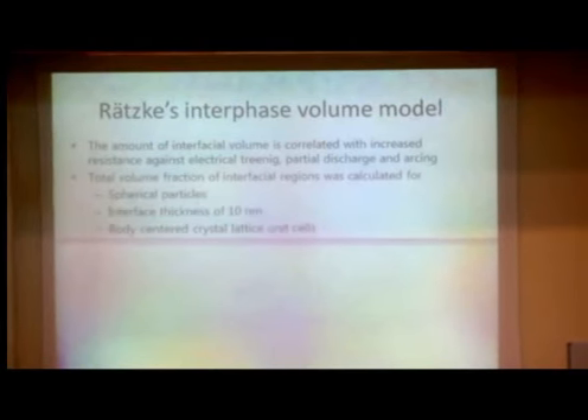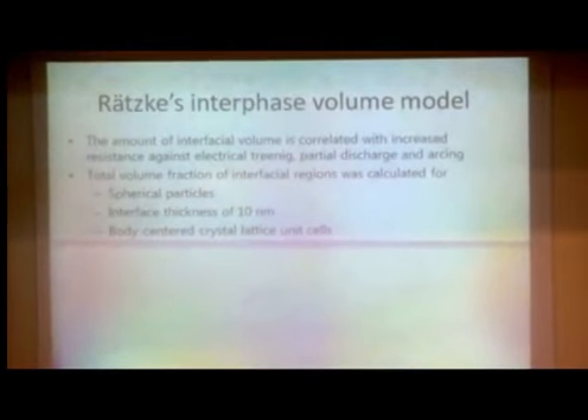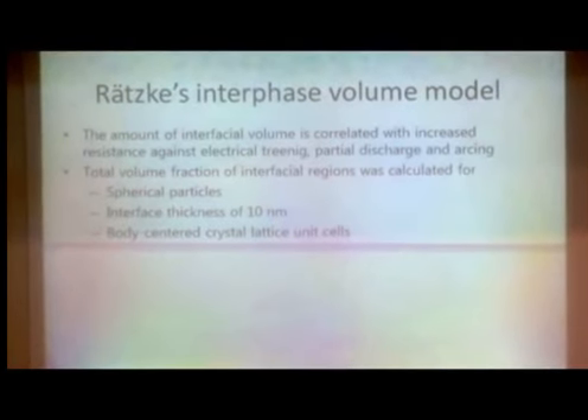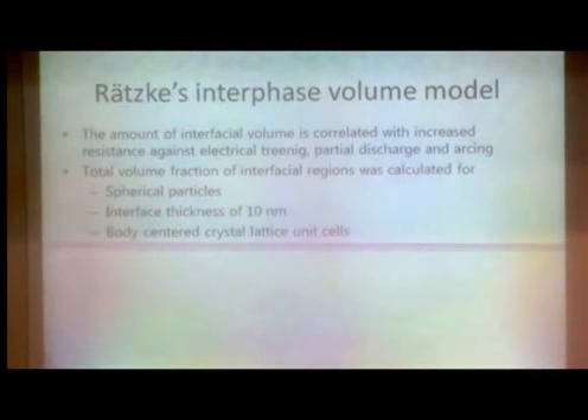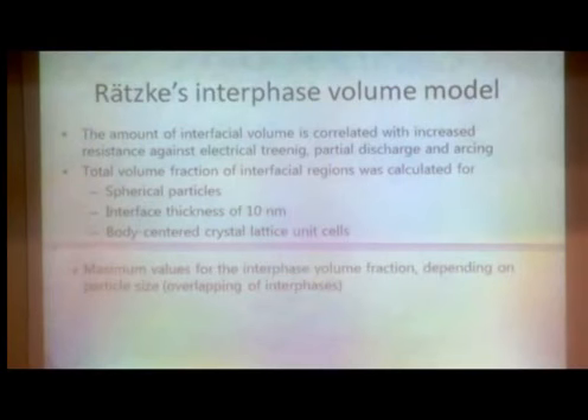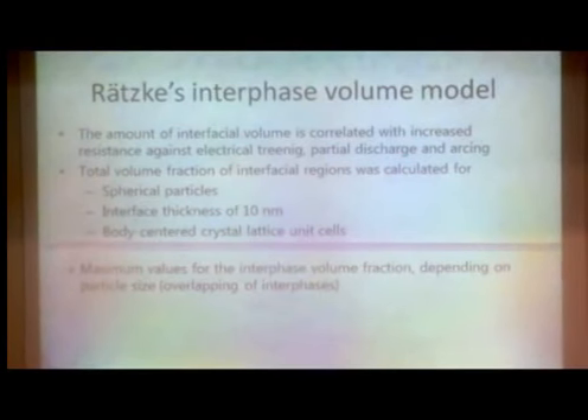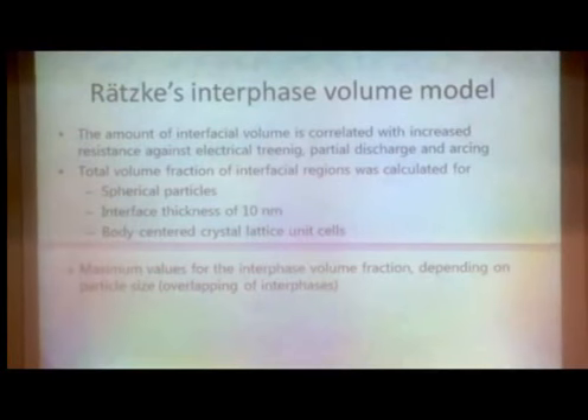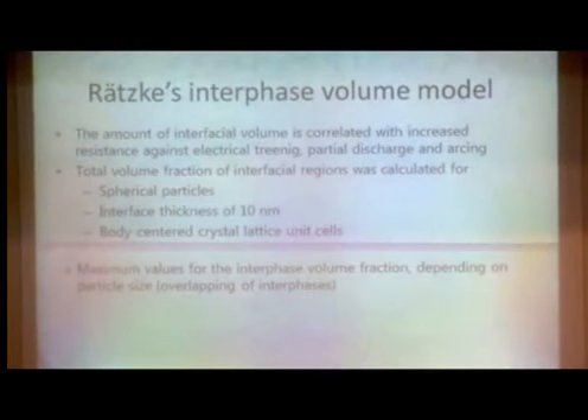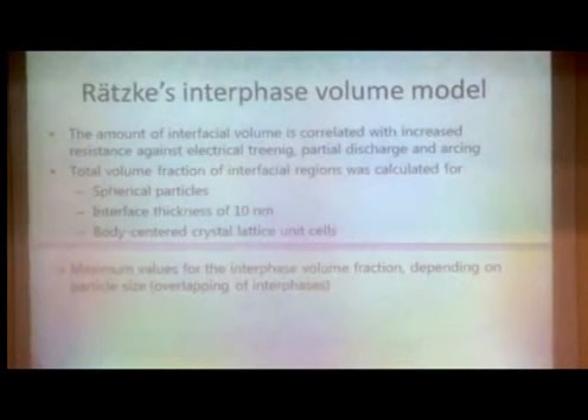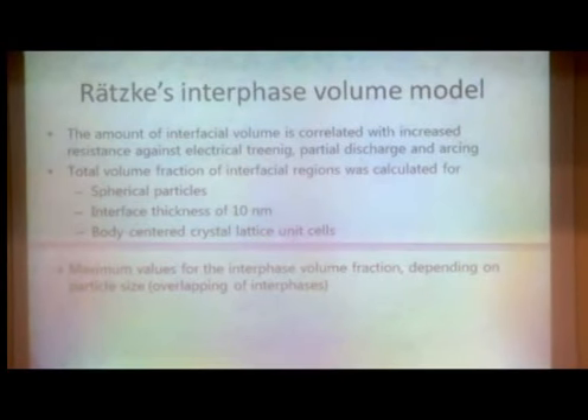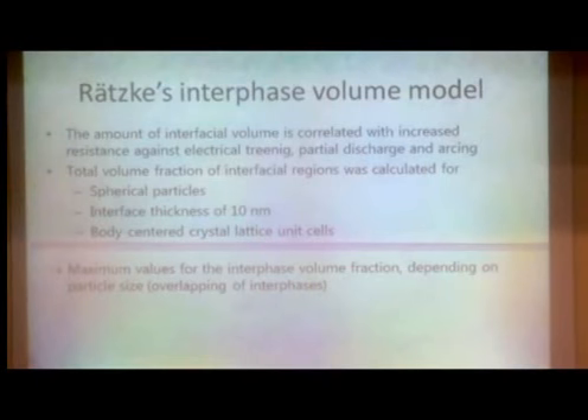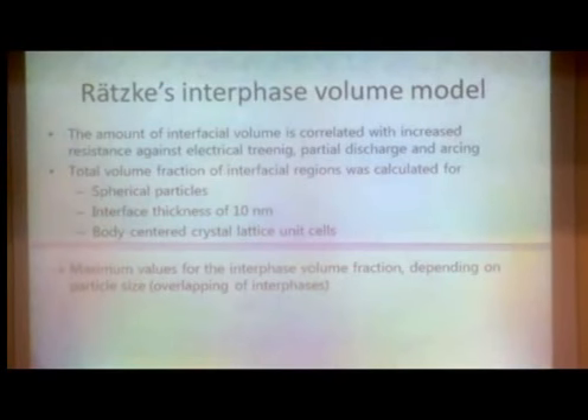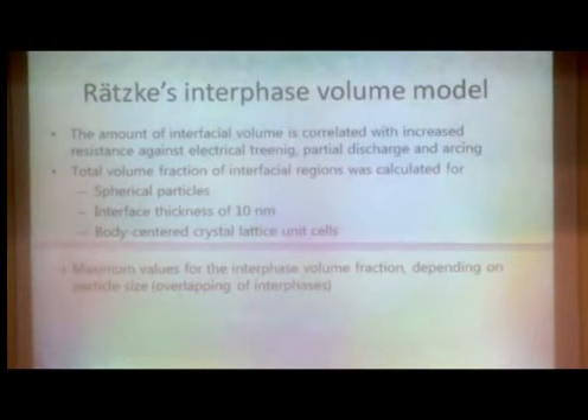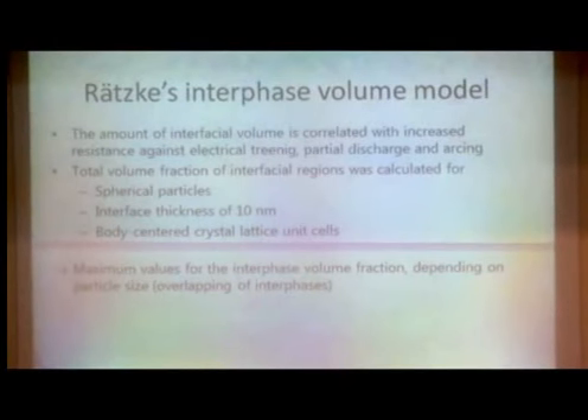And what she did, she assumed spherical particles with an interface thickness of 10 nanometers and a body-centered crystal lattice unit cell. And if you do that, she saw something interesting: you attain maximum values for the interface volume fraction depending on particle size. And you all know, I guess, that there seems to be some magic optimum for the fraction of nanoparticles to change a property.